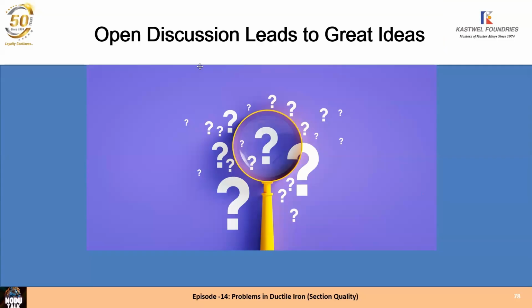Thank you, sir. Now the next question is from Mr. Jait Langardar. Sir, please share the remedies to avoid carbides in a ductile iron casting for thin section parts. One of the things over there, which is mainly the root cause of carbides in a thin section, is a too high magnesium residual content. In my experience, it's in 60-70% of the cases, it's a too high magnesium.